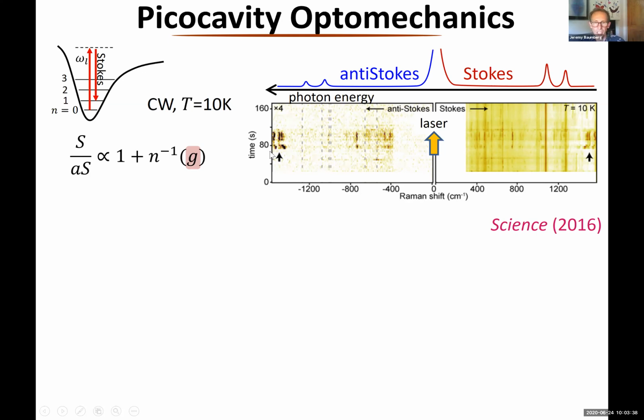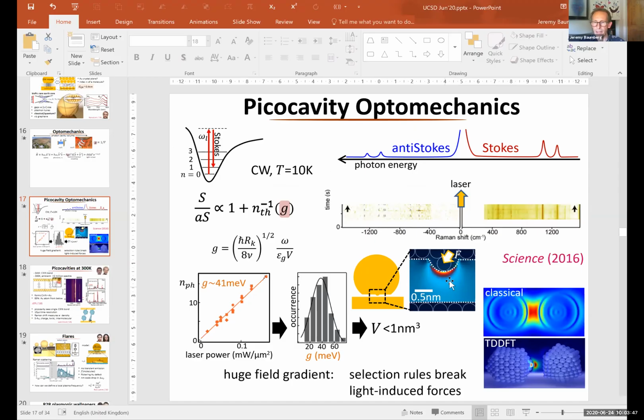But what's interesting is each of these lines here shows a different temperature. And the reason it shows a different temperature is when we look at the molecular coupling here, that molecular coupling is interacting with this picocavity mode in different ways. So the individual optomechanical couplings are different, so their effective driving is different.